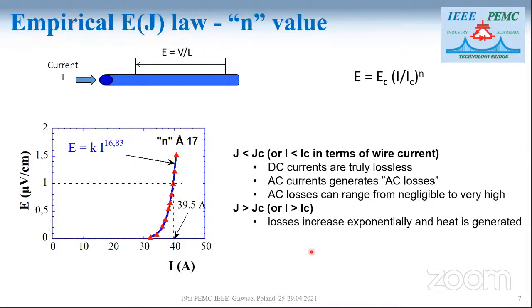A very important fact is the behavior of superconductors. Superconductors, contrary to classical materials, have a strongly nonlinear electric field versus current density behavior law, as you can see on these pictures. It's a characterization of a superconducting wire conducted in my lab, and you can see the electric field versus the current, with this very special shape. Below a certain value of the current, you don't have an electric field, no measurement is possible, and so you can't have losses in this part. The critical current is defined in a standardized way.